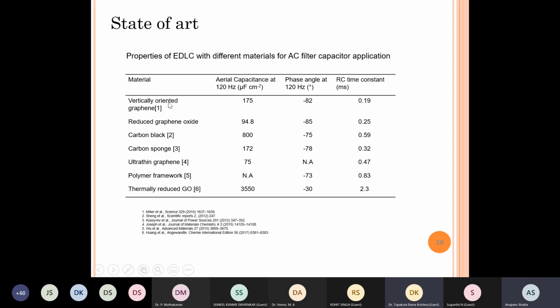What is the resistance? So if you see, all of them are all carbon and mostly graphene based, which means that their capacitive mechanism is EDLC, electric double layer capacitor. And as a result, because you have to maintain straight pores, there is not much increase in the surface area which is possible, and that results in a limitation. Okay, so if one can make a pseudocapacitive electrode with higher frequency response, then because pseudocapacitance is not limited by the surface area that much, it depends upon what kind of redox reaction is taking place, it is possible to increase the capacitance.